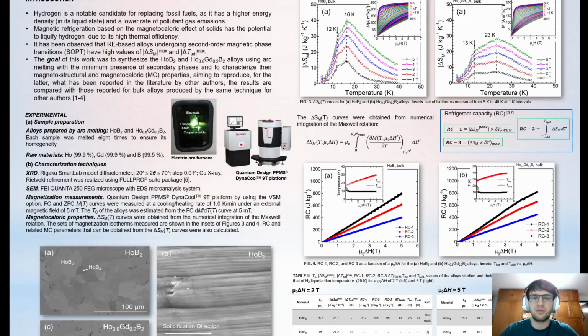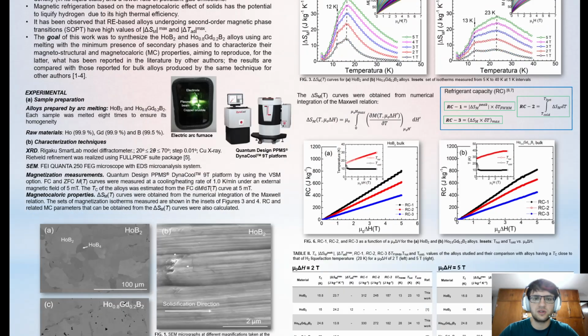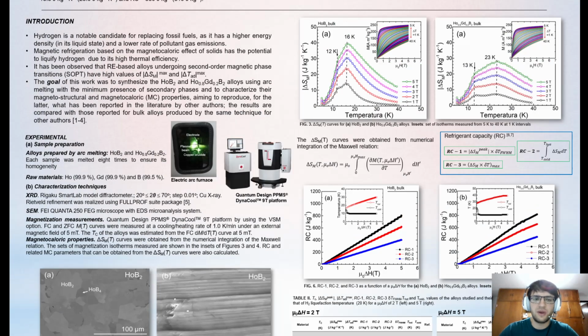Hydrogen liquefaction can be achieved through magnetic refrigeration, which is based on the magnetocaloric effect. The magnetocaloric effect refers to the heating or cooling of a ferromagnetic material under adiabatic conditions when exposed to a change in an external magnetic field. This phenomenon is described by two physical quantities, the adiabatic temperature change and the magnetic entropy change, which are measured as a function of temperature for a given variation in the magnetic field.